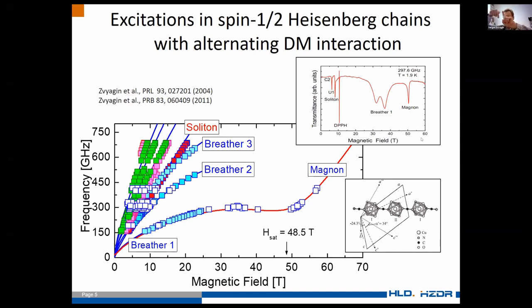So when we have just a flip of the spin on one side, it's not a spin wave, but kind of a soliton wave. So we have localized excitations. But these excitations, while localized in energy, can actually propagate through the sample, magnon-like, spin wave-like. And these are solitons. In addition, we can think about breathers, which are bound states of these solitons.